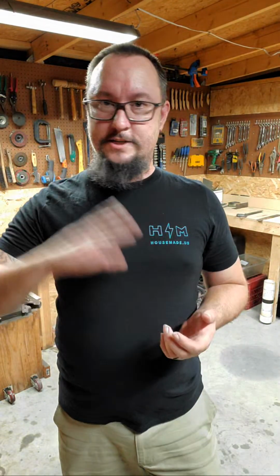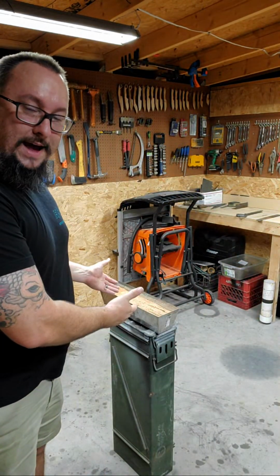So if I would have taken that blade, and I've had a few people say this and people just kind of dismiss what they're saying. So if I would have taken that blade that was about 62, 63 HRC, and I would put it in the oven and temper it down, what would have ended up happening was it would have dropped real far. So I didn't want that. The easiest way to accomplish a tempered blade that had the edge hardness that I wanted and the spine softness that I wanted was to blue it back.